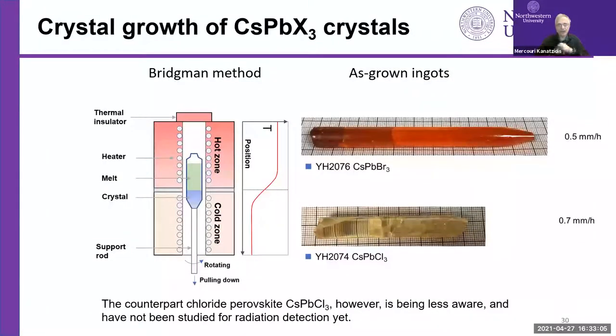So this is the Bridgman crystal. We can then grow it. And you see here, we pass it through a temperature differential. It's high temperature in the top, low temperature in the bottom. We control the gradient, and the material begins to freeze as it's coming down. This temperature is below the melting point, and this is above the melting point. And if you optimize the conditions, you can get a nice crystal that looks like this.